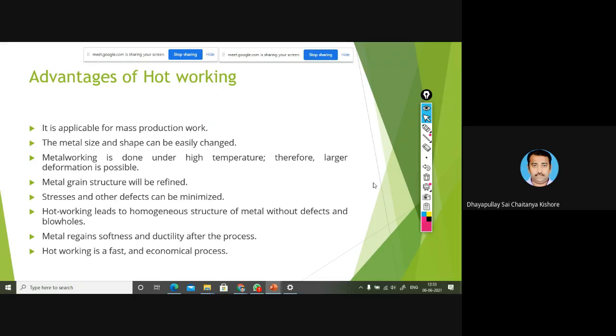The metal texture will be refined here because new strain-free grains form when you increase the temperature over the recrystallization temperature. Due to that, grain refinement happens in hot working, and whatever residual stresses were incorporated before can be minimized. When compared to cold working, the strength of the hot worked component is lower, but we can observe homogeneous properties and structure. The ductility will be good compared to cold working. These are fast and economical processes.